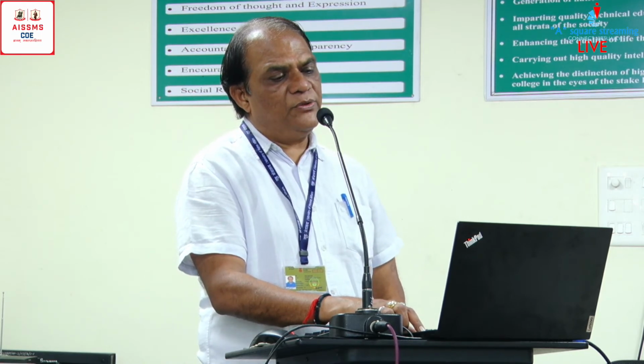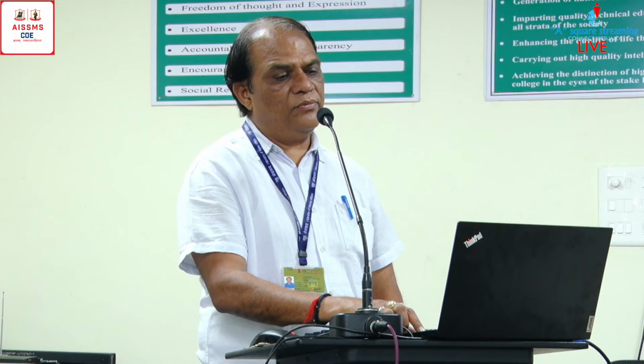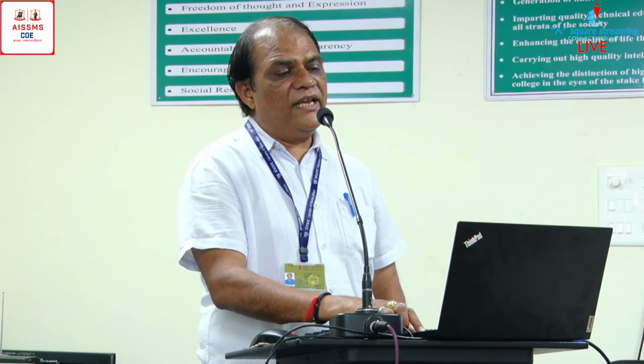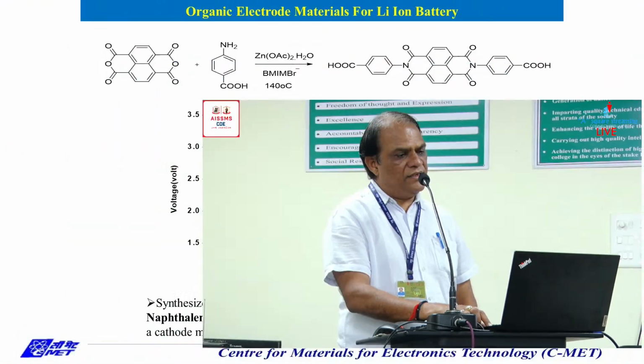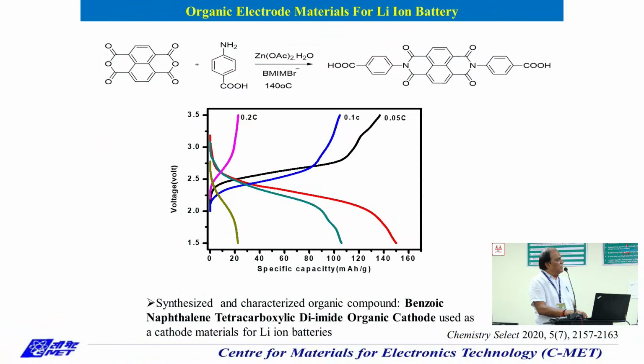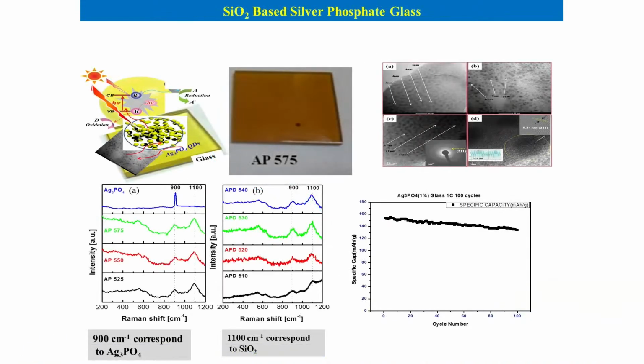All the materials which we used earlier are inorganic materials. So we looked at whether organic electrodes can be used, because they can be synthesized. And we have synthesized one good glass electrolyte. It is a very, very cheap electrolyte, and it can go up to 200 degrees centigrade. So at room temperature, we can charge the battery fast with this electrolyte. This is one of the innovations we have made, and we have taken a US patent for this.